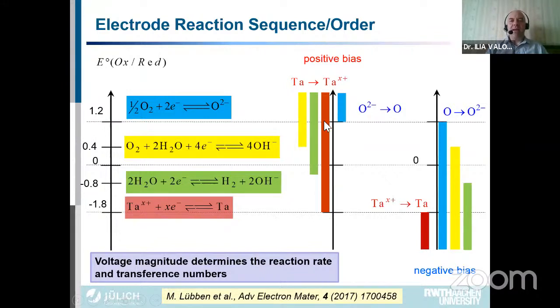If we apply positive bias, the first reaction that will happen will be oxidation of tantalum. So tantalum will be oxidized to tantalum X plus, because it has a very negative standard electrode potential. So even a small applied voltage will cause oxidation of tantalum. But if the voltage is small enough, none of the other reactions will take place. So we can avoid the reaction of water or OH or oxygen simply by applying a lower positive potential.